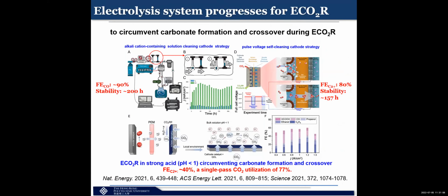Okay, so the other problem is crossover, as we just mentioned. So there are different approaches to tackle the crossover problem. One of the ways is you use a very strong acid, okay, rather than using alkalis. Then you can actually reduce the carbonate formation, because the acid can prevent all this carbonate formation. But the C2 Faraday efficiency for that kind of approach is only about 40%. Okay, and the single pass CO2 utilization is about 77%.